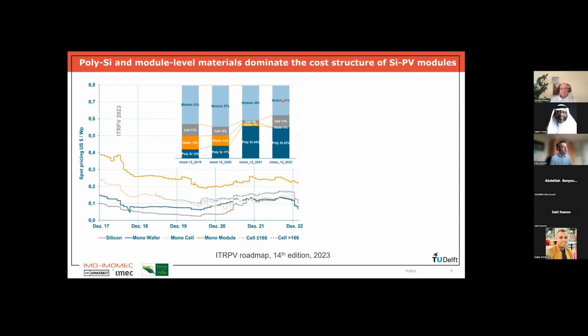Then another 40% is actually coming from the module processing, so to make the module, and especially from the module materials, like, for instance, the encapsulation, the glass, the backsheet. And less than 20% of the cost is actually related to the cell processing. So we can say that the module cost is really dominated by material costs for the polysilicon, especially, and also for the module level materials that we are using.